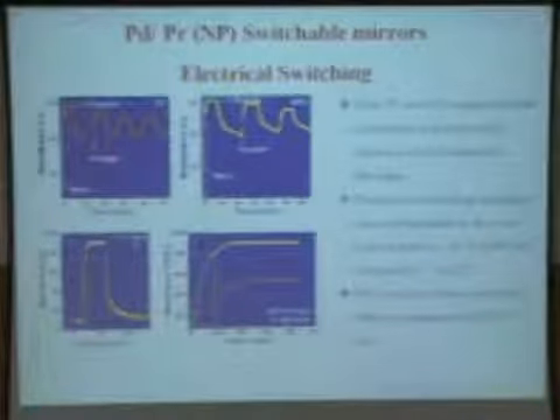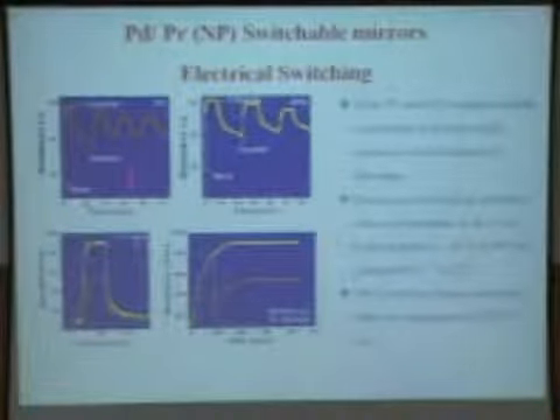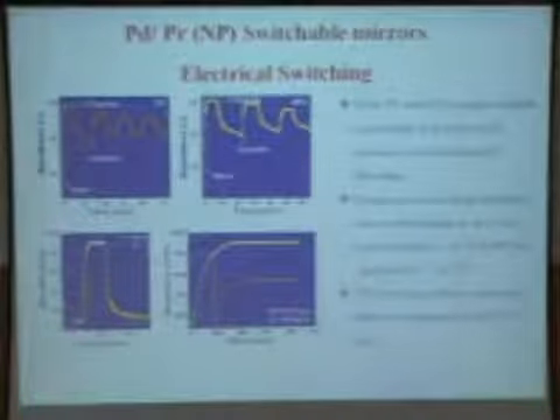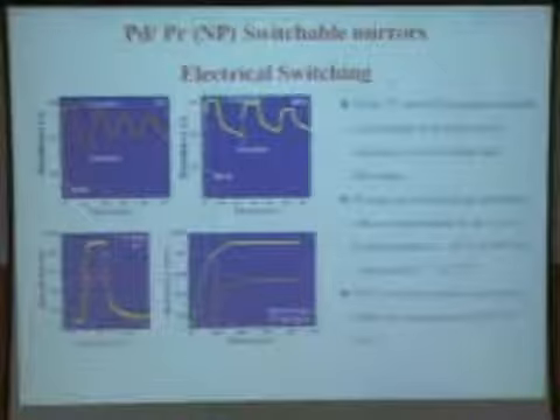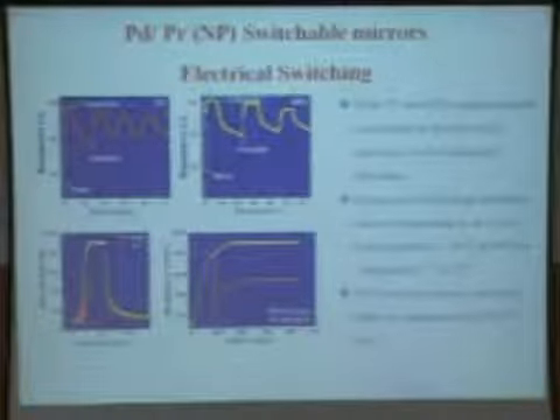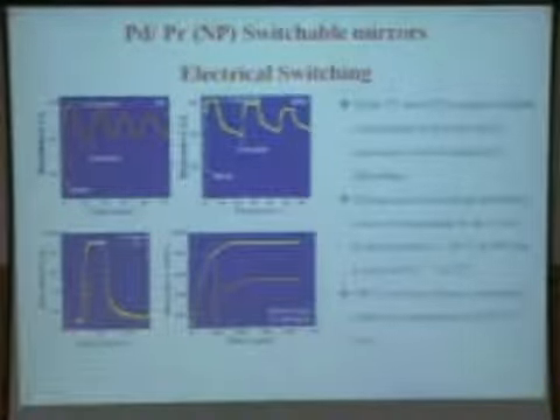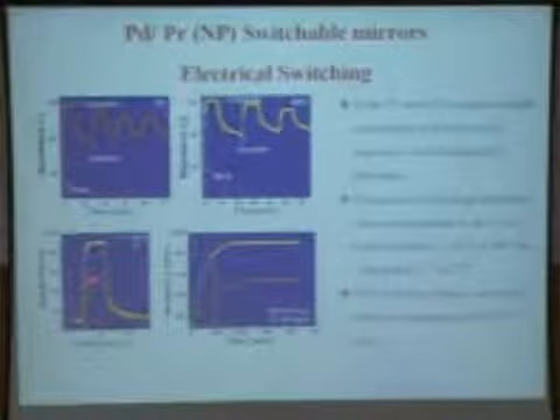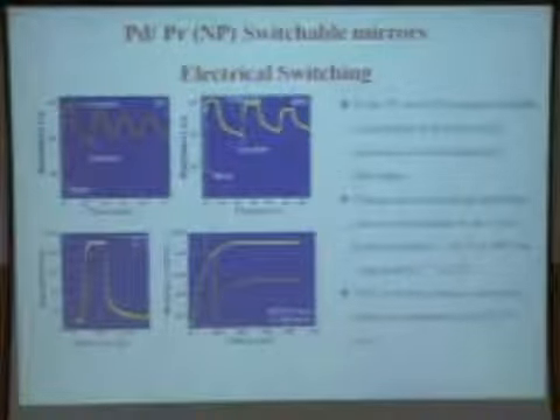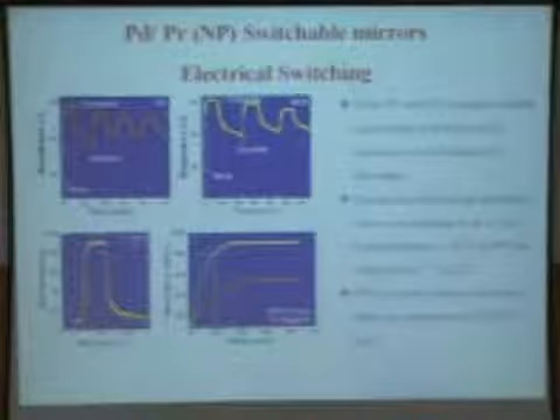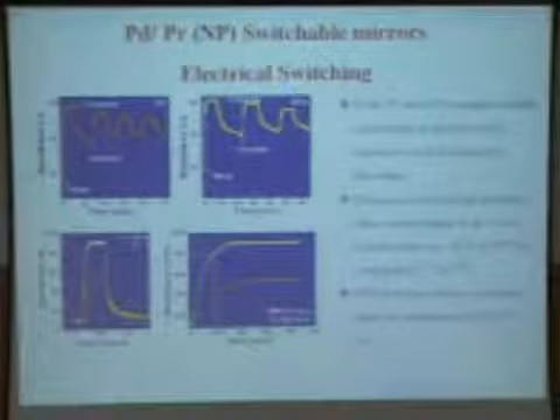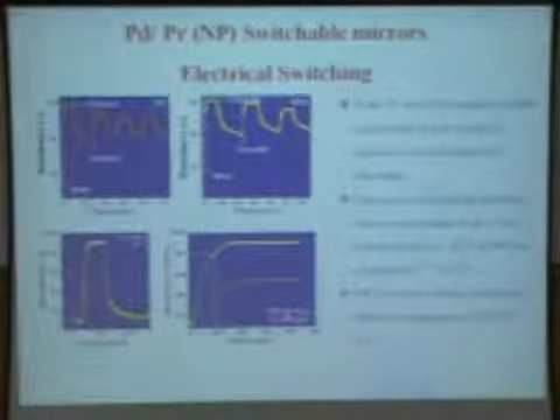You can see that this is in the case of thin film, and this is in the case of nanoparticle. This is the comparison. You can see the yellow curve. In the case of the nanoparticle, the electrical change is something like twice that of a thin film. And you can also calculate the response time. In the case of thin film, the response time is around 150 seconds, and in the case of the nanoparticle, it's around 94 seconds.